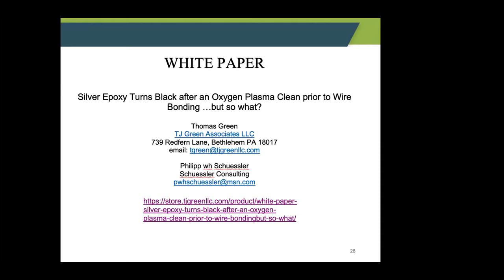In the wire bond, it's just really there to clean up those 30, 40, 50 angstroms of surface contaminants that either maybe bleed out, even resin bleed. Now, if you see resin bleed, it's thick enough you can see it without a microscope, blue light. That's pretty thick. So you're probably going to have to do multiple treatments before that cleans up. But it's a microscopic cleaning difference between argon and oxygen. One is just ablation, more or less. The other is the oxygen has to combine with the organic, which is carbon, and then you produce CO2 and CO, which has to be safely exhausted.